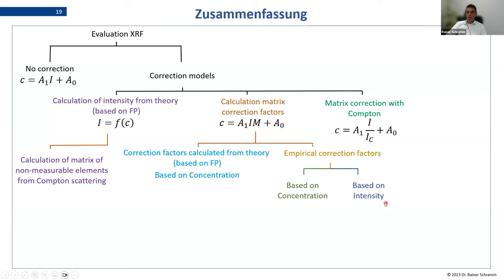But what I told you, I always recommend to use concentration-based models because they have a much better performance in doing matrix correction. Be always careful that you only include matrix correction from elements where the concentration is significantly high and where your standard set is really representing these kind of corrections. If not, you get an overcorrected model, and then your results may go wrong.